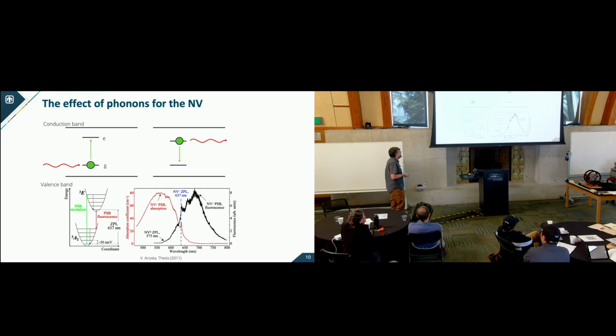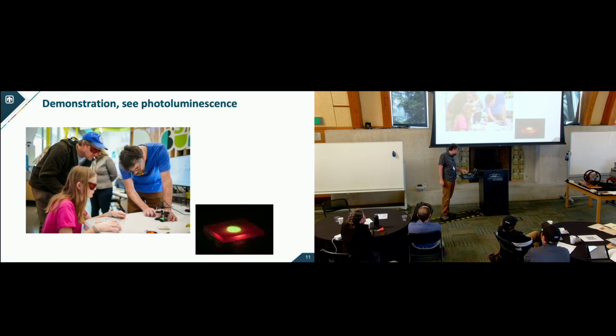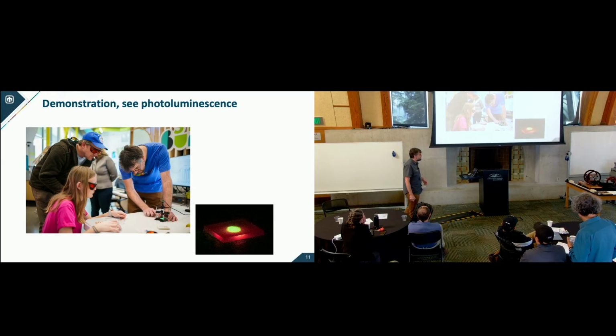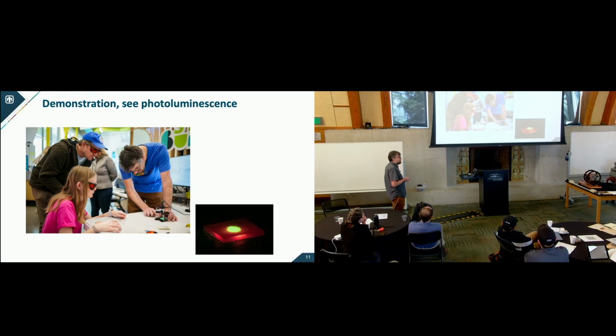So one of the demonstrations that we'll do, and I've got a nice picture from where we did it at Children's Museum, is that I have a little demo with a diamond that's full of NVs. You can pump it with a green laser, wear some optical glasses to screen out the green, and you can see a very bright red glow from these diamonds. Okay, so the thing I liked about this is that it's an actual observable effect with your eye in a very simple experimental setup, and we'll take a look at that later.